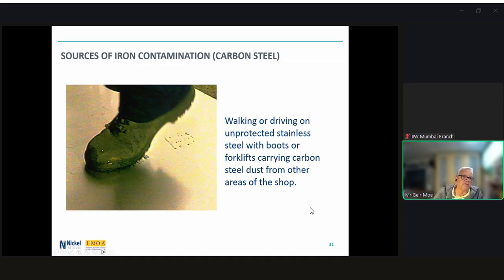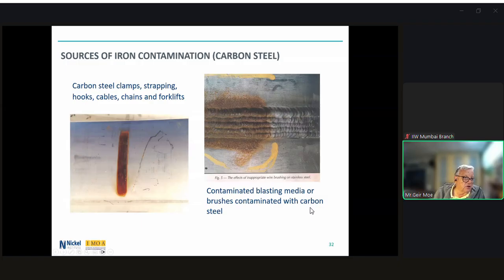And then another source of iron contamination is the same. It's just carbon steel dust. Carbon steel particles can be transferred to a stainless steel surface by walking or driving on unprotected stainless steel with boots or forklifts carrying carbon steel dust from other areas of the shop. Stainless steels can also be contaminated by contact with steel packing straps and handling equipment made from carbon steel, or by contaminated blasting media or stainless steel brushes contaminated with carbon steel particles.